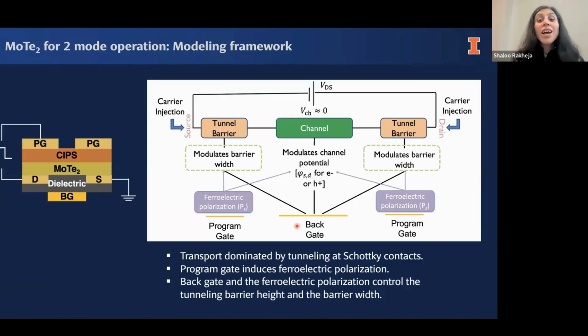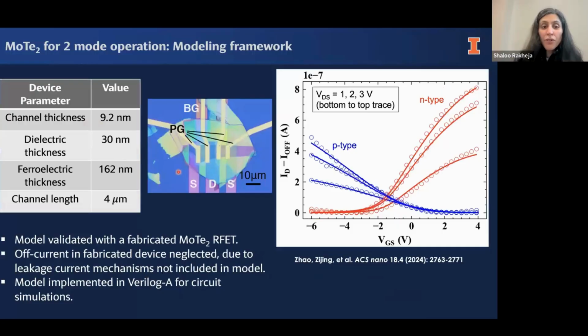So for those purposes, we have developed a Verilog A model that captures the essential physics of these Schottky barrier devices. Remember, these are Schottky barrier. These are not ohmic contacts, because what we are doing is we're either injecting electrons or injecting holes from these drain or source through a Schottky contact that exists between the semiconductor and the contact. So these devices are not going to be as good as your front end of line transistors because their current is always going to be small. So that is one thing that we have to remember.